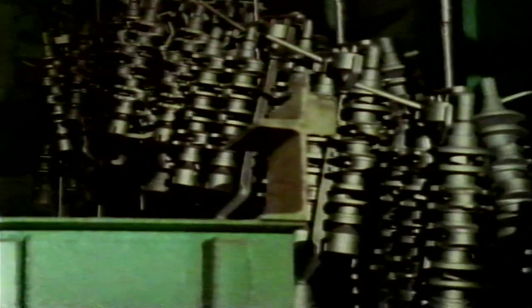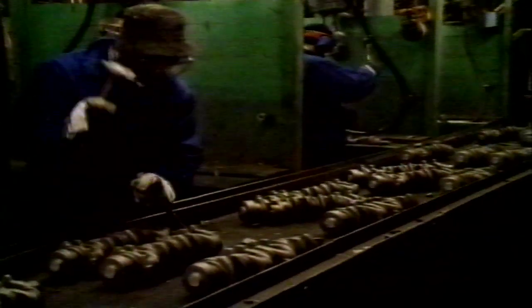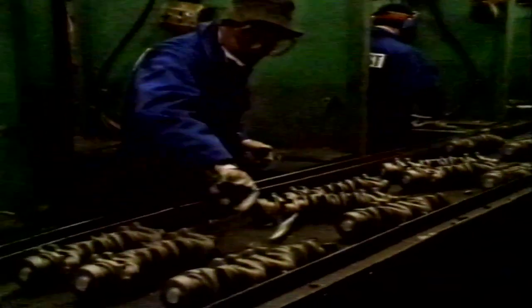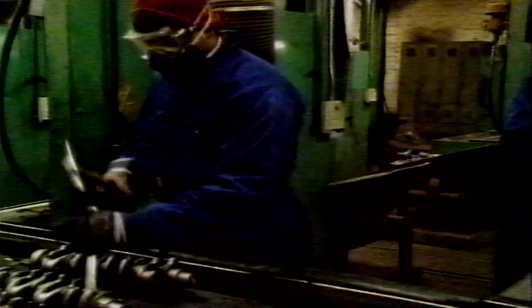Each casting is now cooled in air on this continuous conveyor for 65 minutes. The casting is shot blasted to remove any sand or resin sticking to it. It also gives the crankshaft a much more pleasing appearance. Finally, the running and feeding system is removed from the casting, and each crankshaft is hand finished to remove any unwanted material or flash. This is a very efficient foundry, and it only takes 4.5 hours for a crankshaft to be produced from pouring to dispatch.